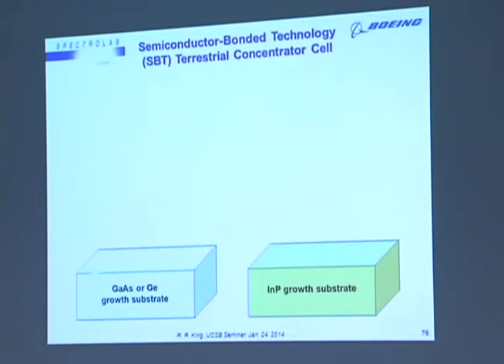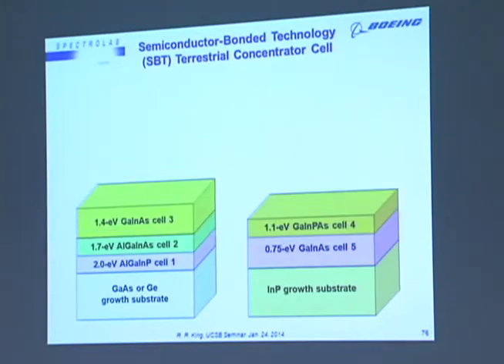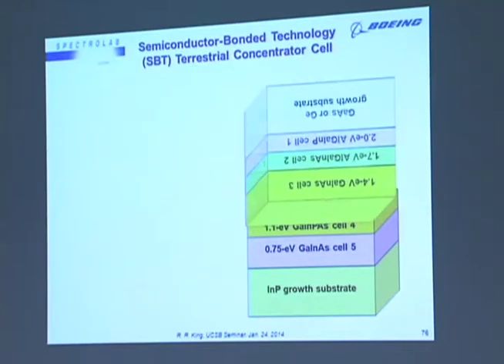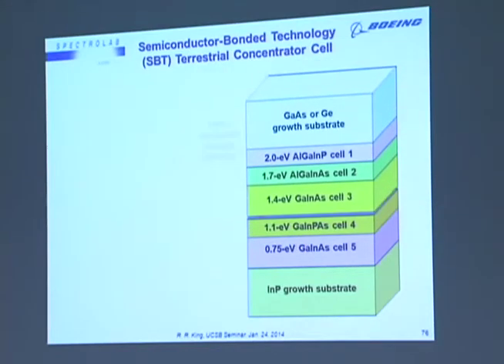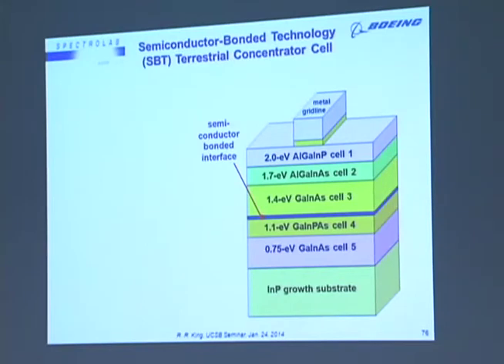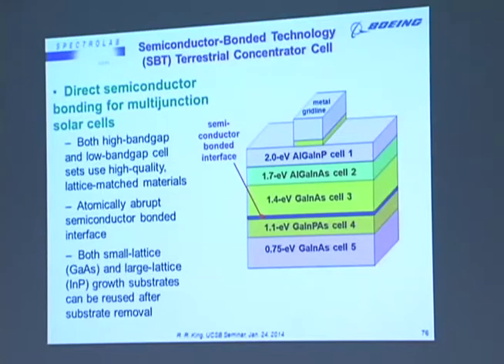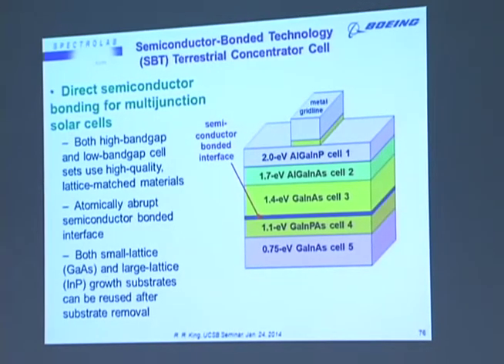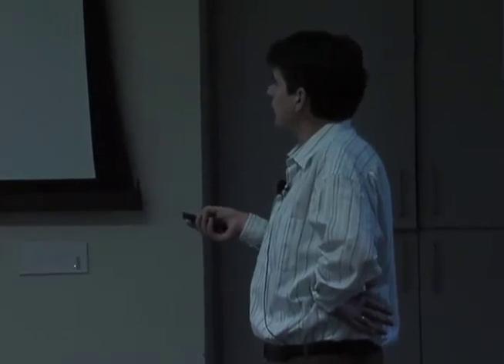We start out with 2 different substrates, a gallium arsenide substrate and an indium phosphide growth substrate. We grow the upper 3 cells inverted, and we grow the bottom 2 cells upright on the indium phosphide substrate. That cell is then flipped and bonded to the lower combination of subcells. We then remove the gallium arsenide growth substrate, put on the metal grid, and then we have a direct semiconductor bonded multi-junction cell, which allows us to achieve very high crystalline quality in both the high band gap and low band gap cells. So this is a photograph of the cells themselves and the IV curve for the 37.8% efficiency 1-sun cell.